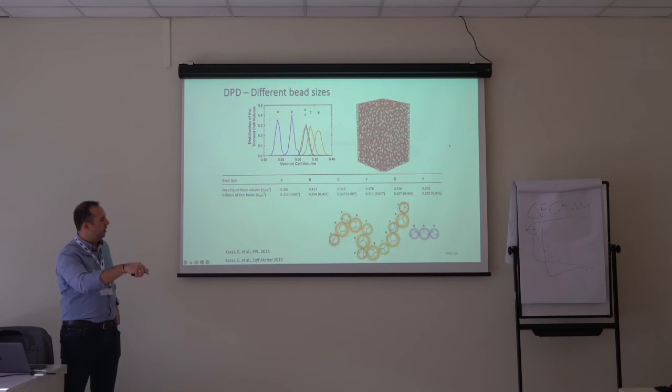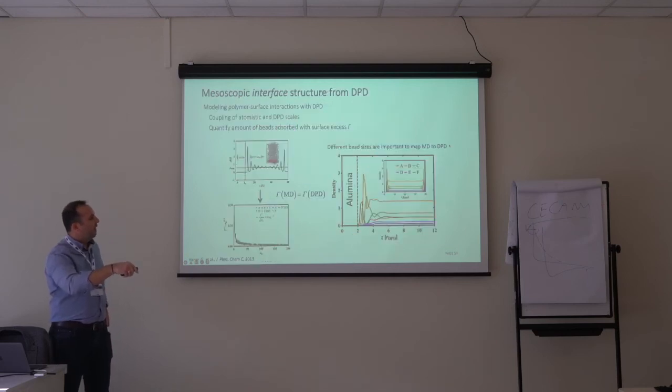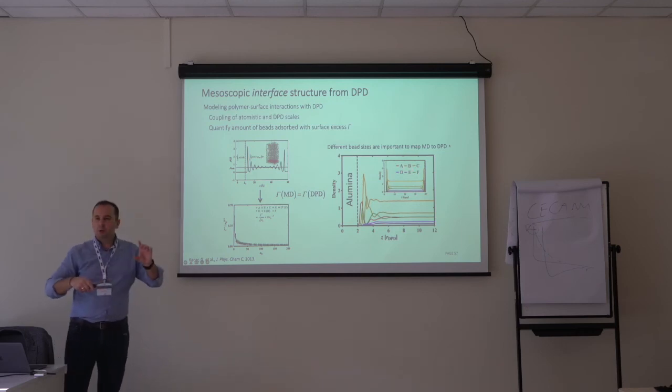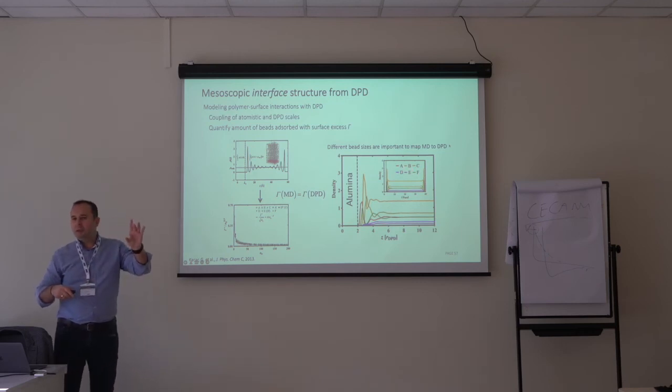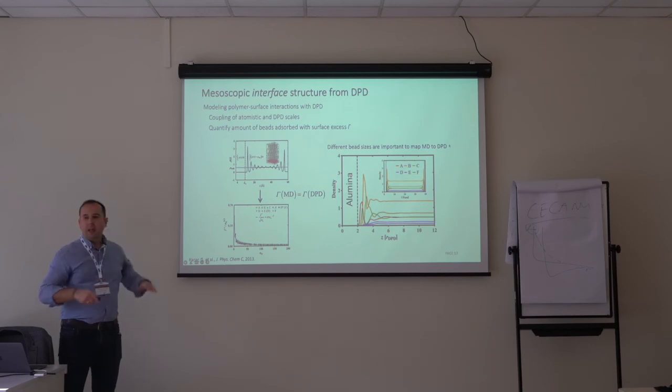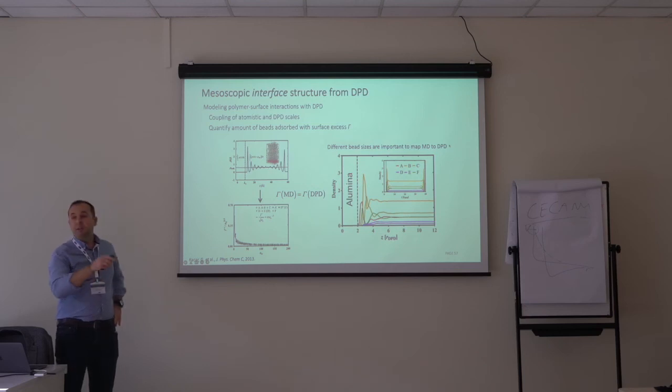It's not quite clear, but all beads are represented by different names. For each functional group, we have just a monomer above that surface, and we parameterize the interactions between the monomer and the surface by running molecular dynamics simulations with the pure liquid density.